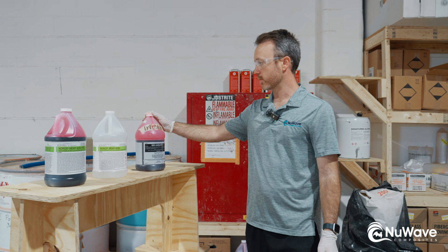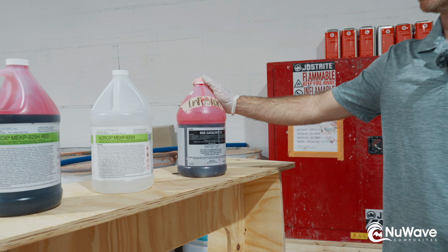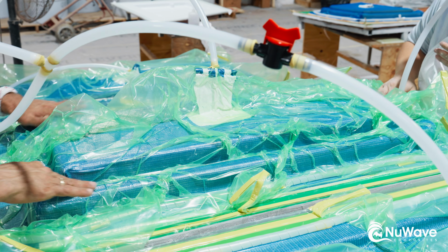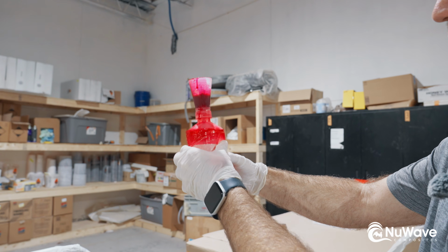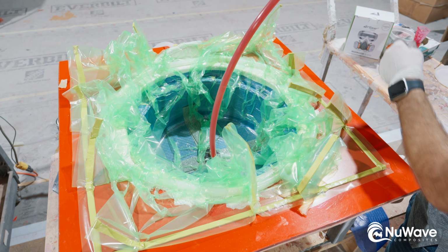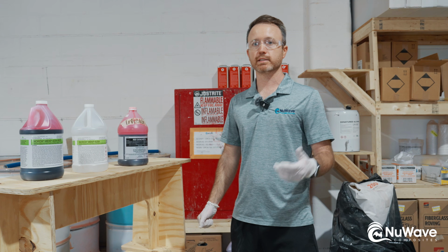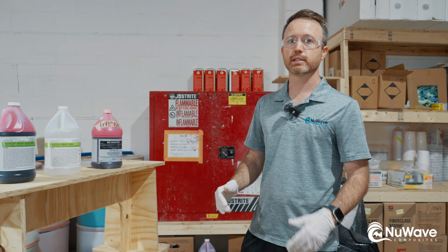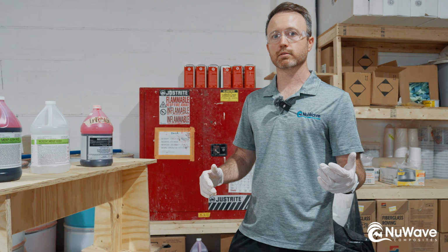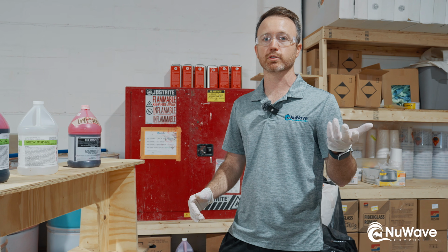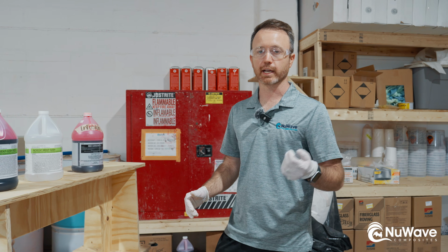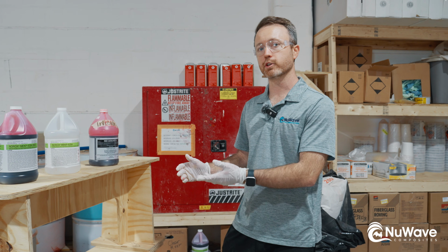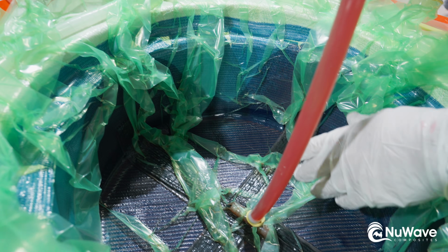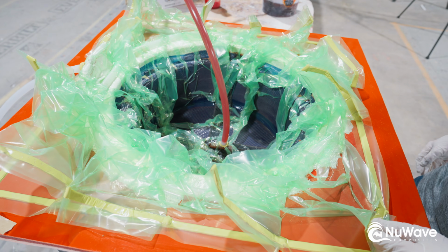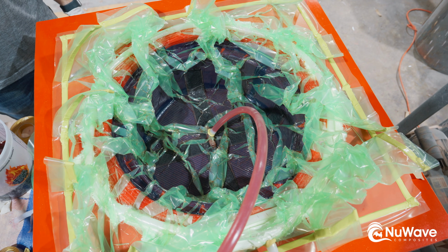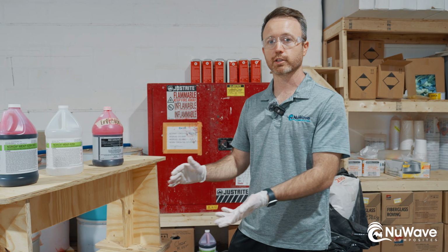And then the next one we have here, we typically use this in infusions, especially for larger parts. This is Red Catalyst 11. So this is a blended catalyst. So it's a combination of the MEKP and CHP. So what that blend does is it helps with reducing the exotherm, or the max temperature that the part sees during the cure cycle. So that's really well suited for infusion, where you have a big stack of laminate and all this resin that's kicking off at once. So it keeps that temperature down and gives you a little bit more window for that cure to happen.